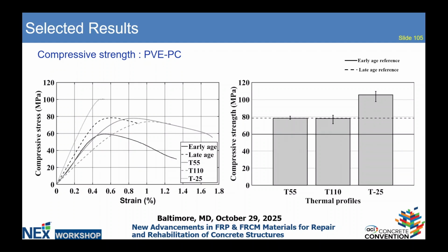Similarly, for polyvinyl ester polymer concrete, you can see 2 reference lines there. I thought polymer concrete wouldn't have any late increase in compressive strength, but you can see the difference between the dark line and the dotted line. Polymer concrete still gains some strength even in late ages, although we say that the reaction is instantaneous. And on the thermal part, there is no degradation in compressive strength, and in the extreme negative temperature, there is an increase in compressive strength.